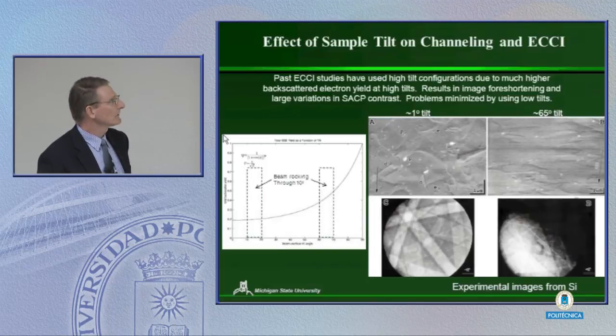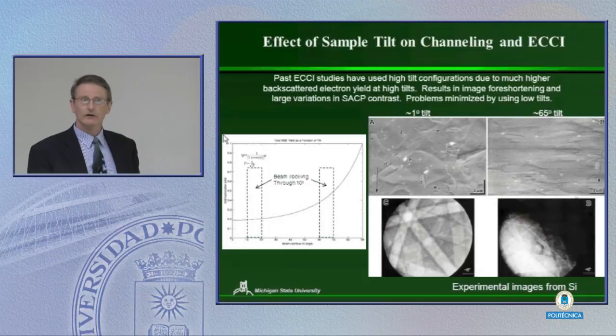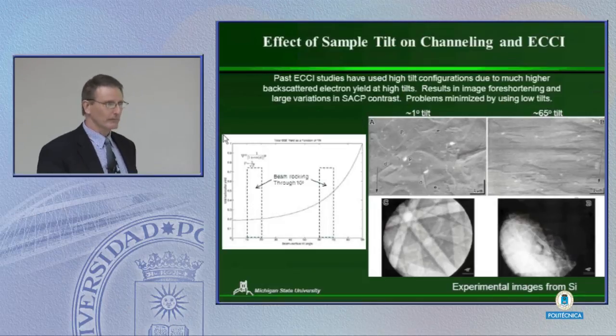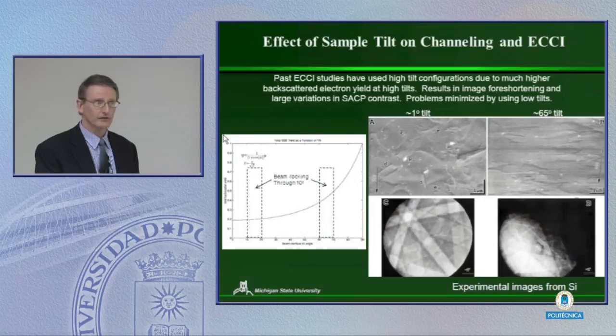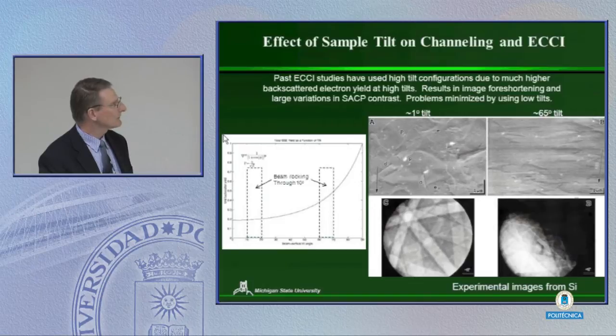I want to take a second to talk about how we do our approach versus other people. A lot of people actually do this at a fairly high tilt configuration. And the reason is your backscattered yield increases as your tilt increases. And so typically EBSD is done at large angles, and that's the reason for doing them at large angles. That, and also you can fit a camera on the side of the chamber, and you can't put a camera right on top of the pole piece of your microscope. And so that certainly is an advantage because you'll get more signal at higher tilts.